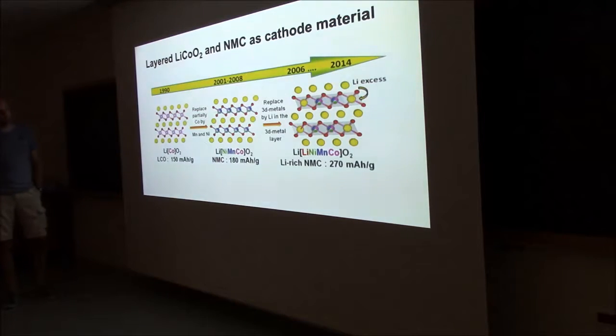Now, let's say in the 2000s, they partially replaced the cobalt because it was too expensive. They partially replaced it with nickel and manganese, but it also increased the energy capacity a little bit. So that was an extra advantage. And then, let's say something like 10 years ago, they started to put extra lithium at the positions of some of these nickel, manganese and cobalt.